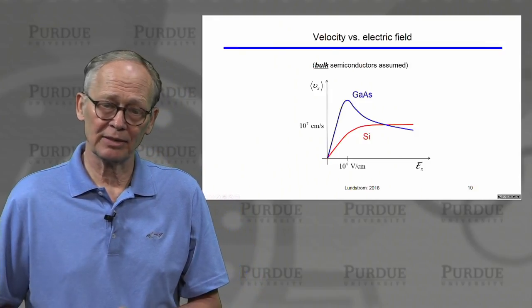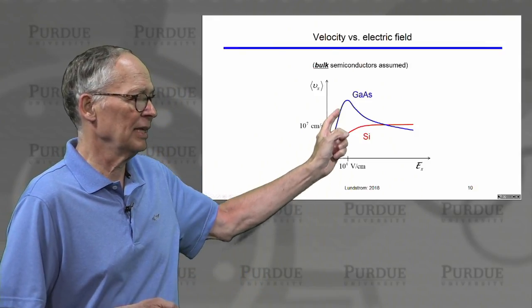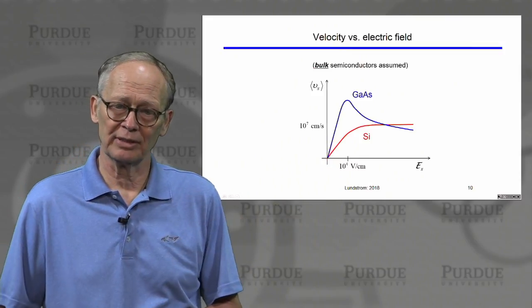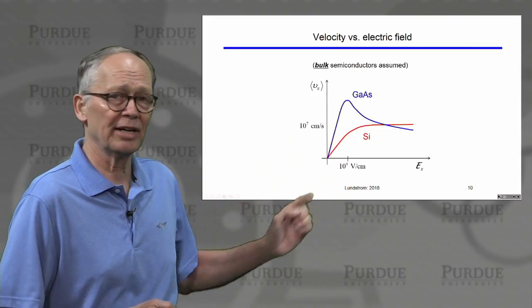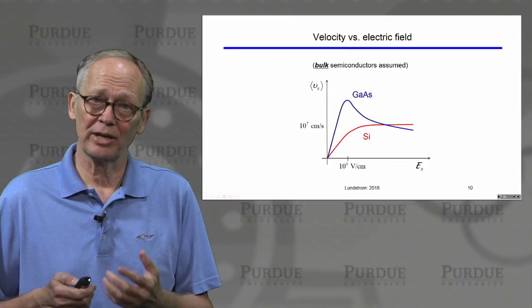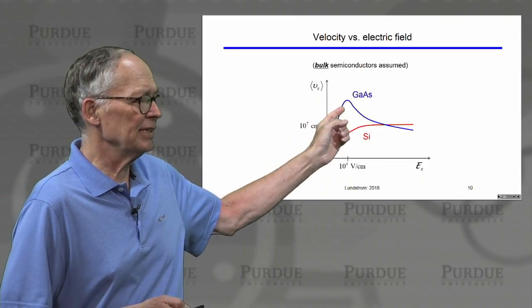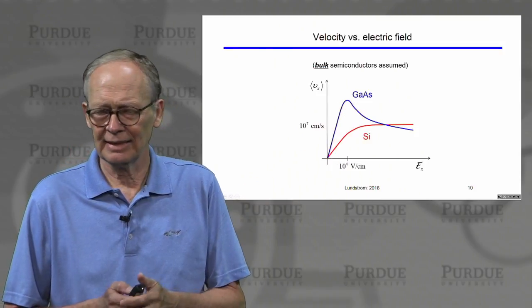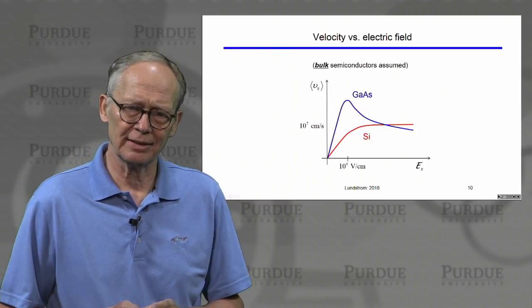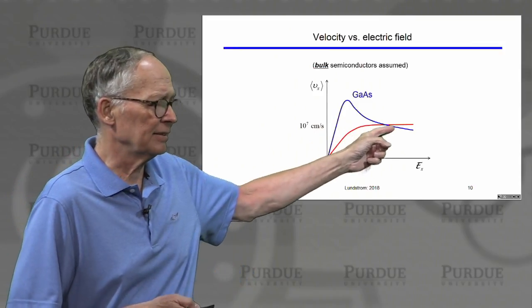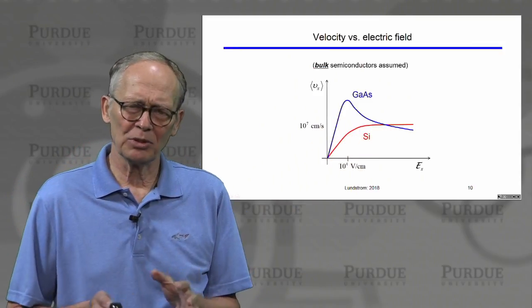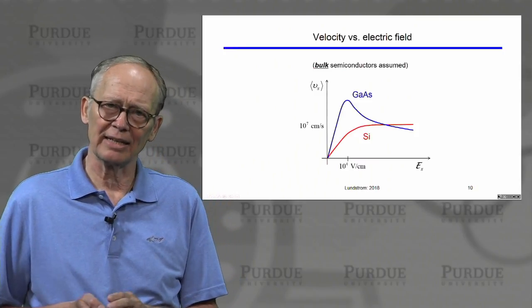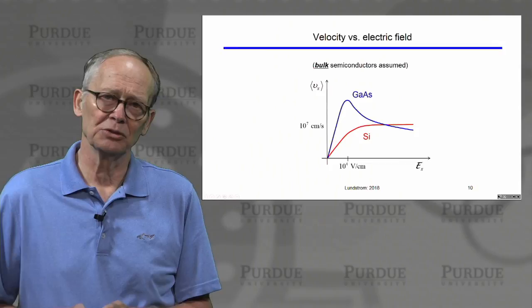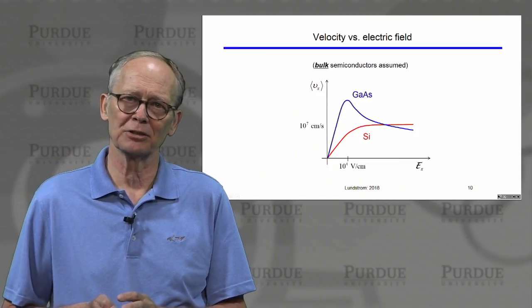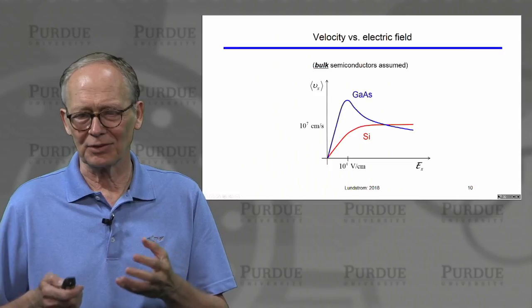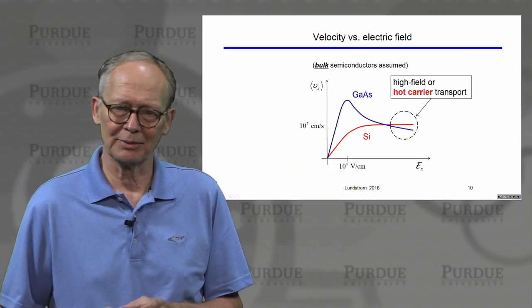If we look at different semiconductors, we can see that under low fields, the velocity is proportional to the electric field in gallium arsenide, but the velocity is much higher, indicating that gallium arsenide has a much higher mobility. At higher energies, there are some complicated things that take place. Electrons move to different valleys in the conduction band, the scattering increases, the velocity drops down, and in almost any semiconductor, you will find that under high electric fields, the velocity is reduced to on the order of 10 to the 7th centimeters per second. That's sort of the speed limit for electrons and holes in bulk semiconductors.